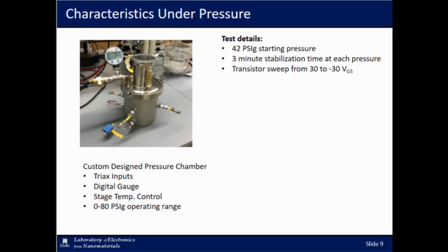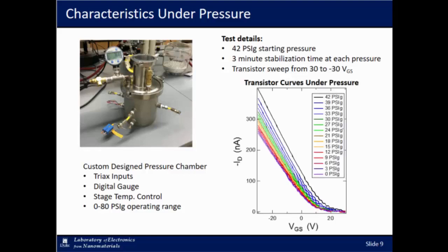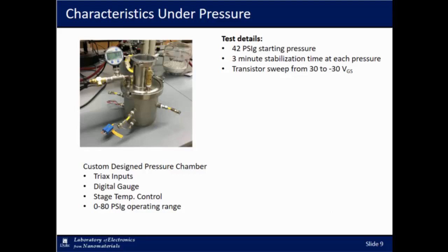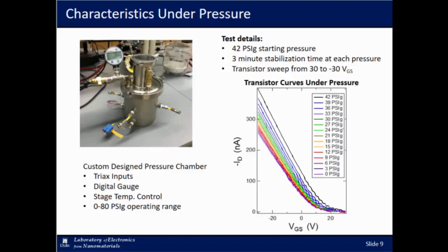For this work, I do use pounds per square inch because in the US, the tire industry, that's all they use. But just to give you a conversion factor, the maximum I use is 42 psi, and that converts to about 300 kilopascals. So if you're looking at my plots, the maximum is 300, the minimum is 0 if you're more used to kilopascals. And so for the test details themselves, I start the chamber at 42 psi with the sensor inside. I let it stabilize for 3 minutes, and then I do a transistor sweep from 30 to negative 30, and I do a full hysteresis sweep just to make sure that the transistors are all starting in the same initial condition.